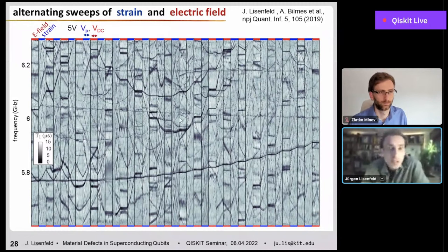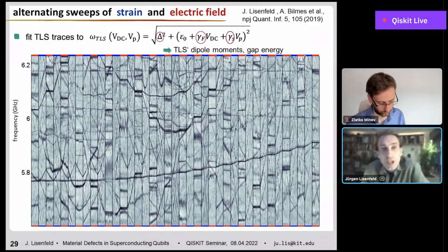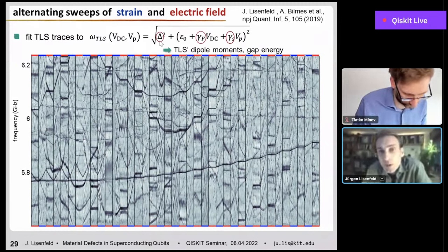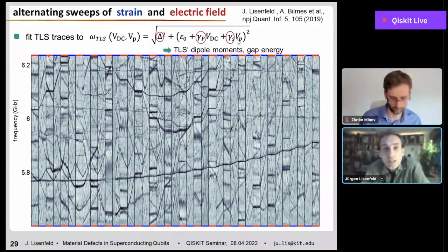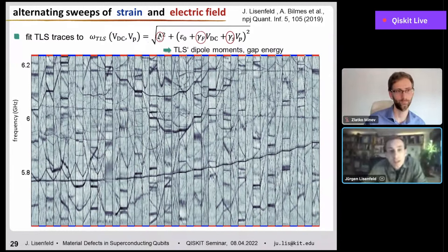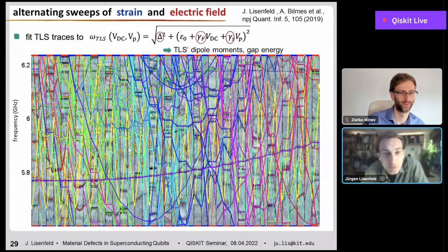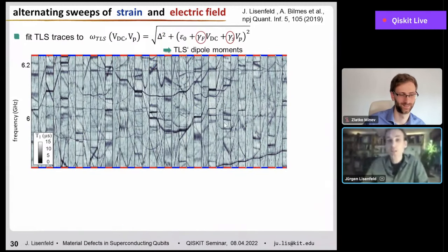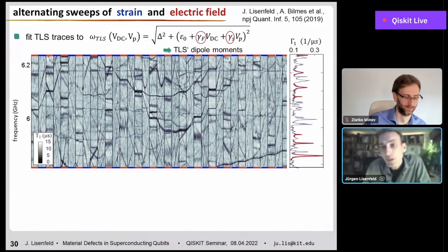Yeah, and then you can fit all these traces to the hyperbolas, depending, of course, on three parameters: the field, the strain, and the tunneling energy. And this is how such a fit to all these resonances looks. So yeah, you can get colorful insights from these fittings. And also you can look at each individual vertical cross-section through this data, which then, of course, reveals the coherence and resonances of each defect.